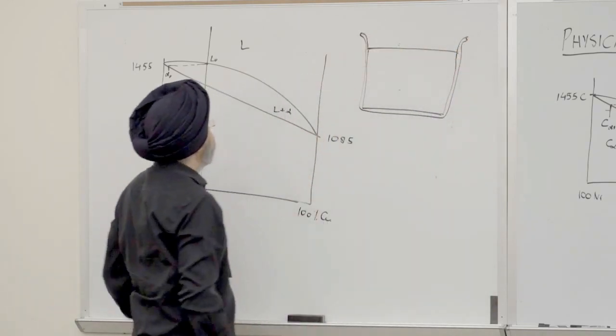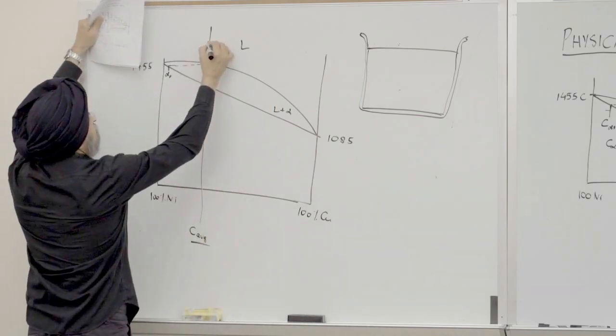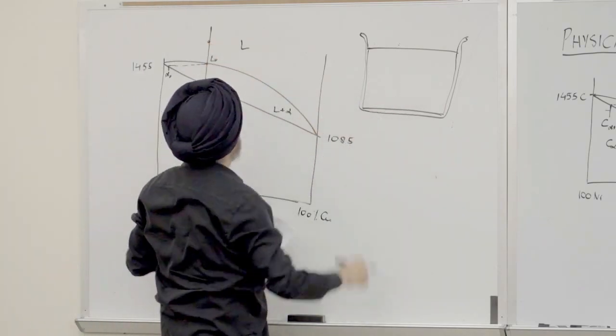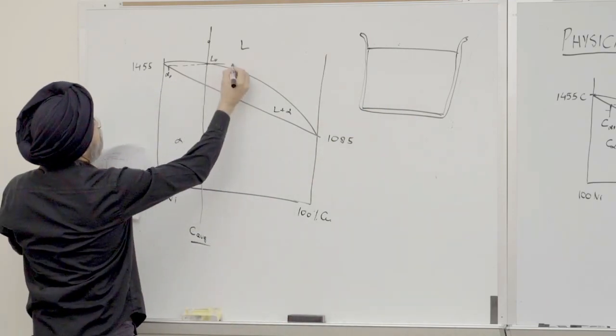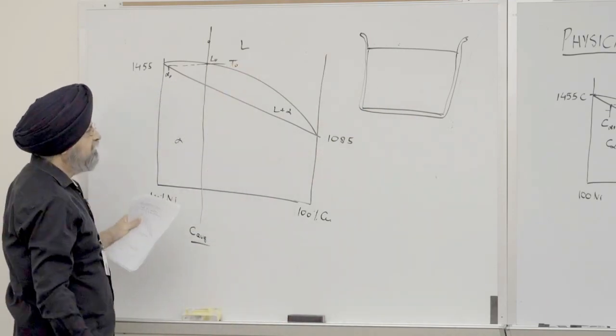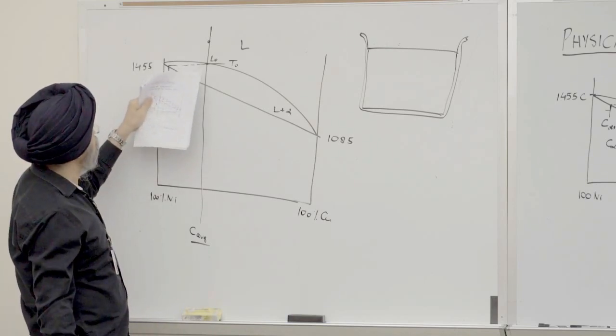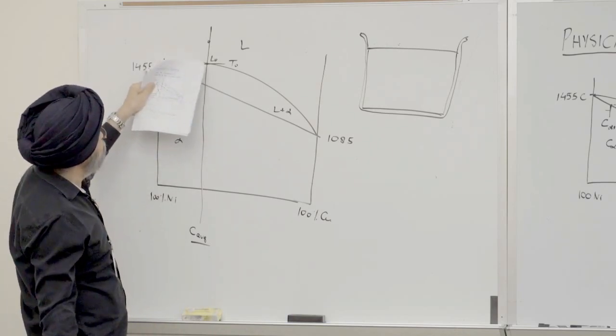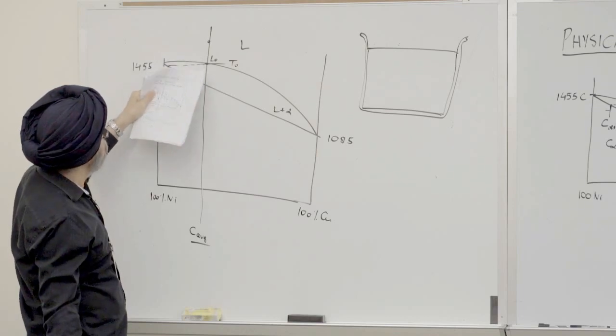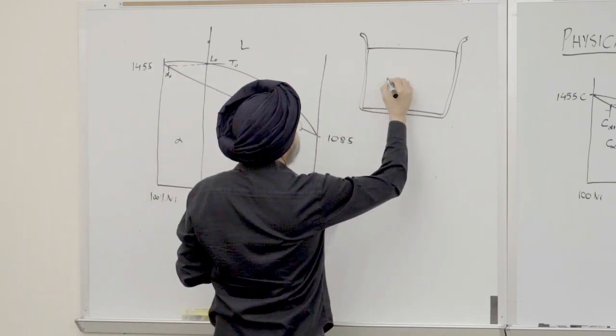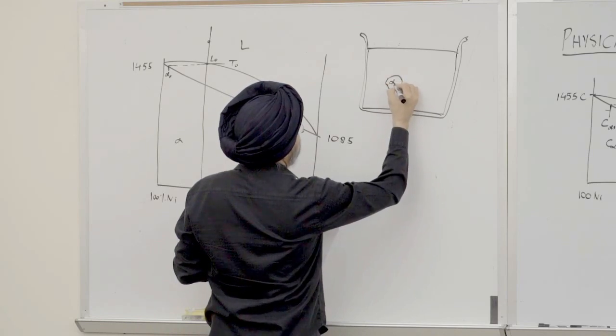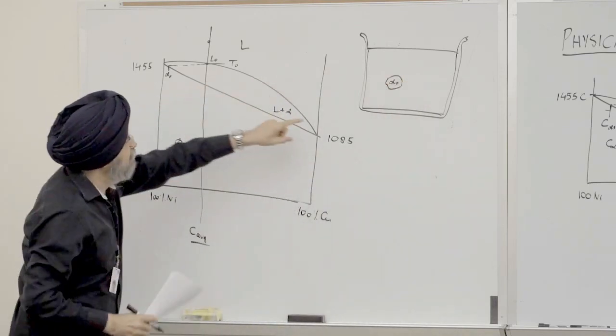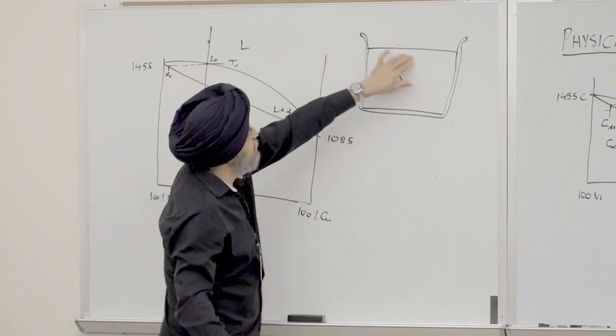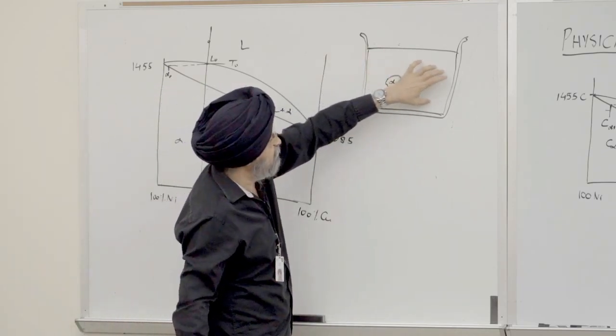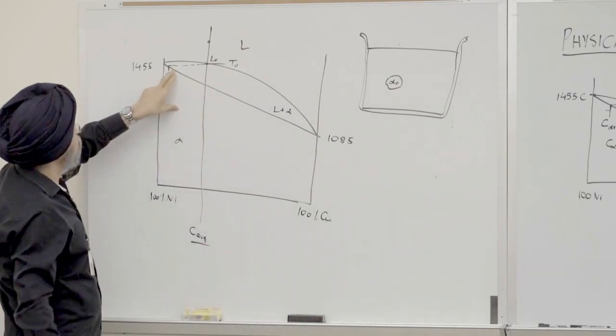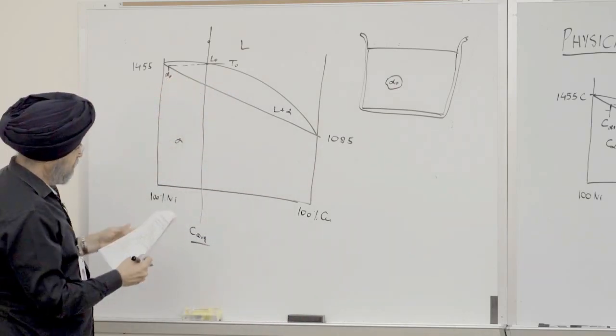And we have liquid. So we are at a temperature over here, so everything is liquid. But at this temperature, let's call it T0, because we are fast cooling, let's assume that even with the fast cooling, you get some, I'll just draw one particle of composition alpha naught. Actually many solid particles freeze out, but let's only draw one. So that particle has composition alpha naught.